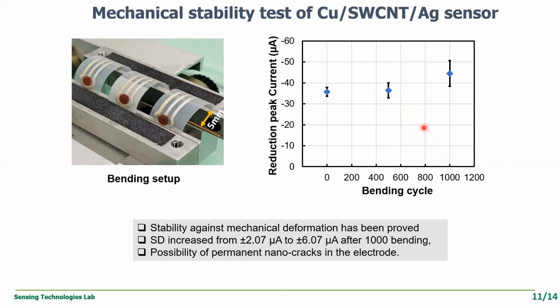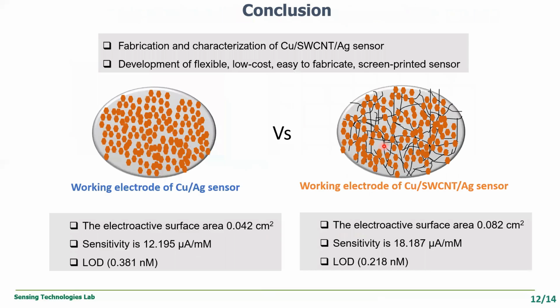Finally, we go for the mechanical stability test. Here, the bending test was done with the help of a customized bending setup, where the bending radius was 5 millimeter. We experimented with 500 and 1000 bending cycles, and from the result, the stability against the mechanical deformation has been proved. Though the standard deviation increased from 2.07 to 6.07 after 1000 bending cycles, which is still within the range. This is because of the possibility of some permanent nano cracks in the electrode.